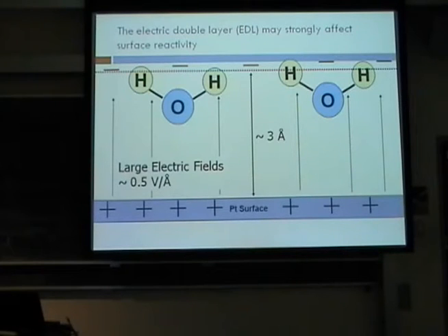And there are basically two main effects that have been probed in those studies. And the first of those is the fact that, okay, we have a charged surface here. It's a positive charge that's causing electrons to want to go there in the case of the oxygen reduction catalyst, in the case of the cathode. All right, and so because this has a positive charge, you have a thin layer of liquid in practice over the surface of the catalyst. And there will be charges that accumulate close to the surface in the liquid that preferentially orient a more negative charge in the solution phase.